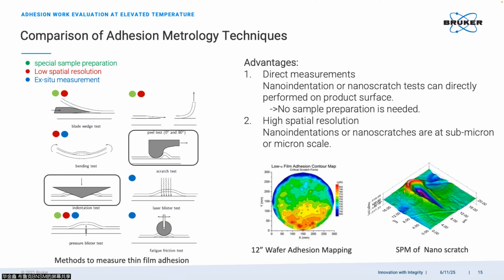The interesting thing is you can see the uniformity of your interfacial bonding is very bad. You have a very strong interfacial bonding on this half, and a very weak interfacial bonding on the other edge region. So this is, I would say, the second main advantage when we apply the indentation method or scratch method, which is the high resolution.